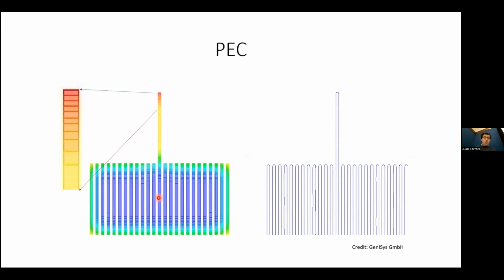The blue doses are the lowest doses, and the red doses are the highest doses. So you can see how the dose keeps increasing for the line. Similarly, at the corners and on the edges of this grating, you have increased dose. And then once you convolve this and develop it, you can get something that's pretty close to what you designed.